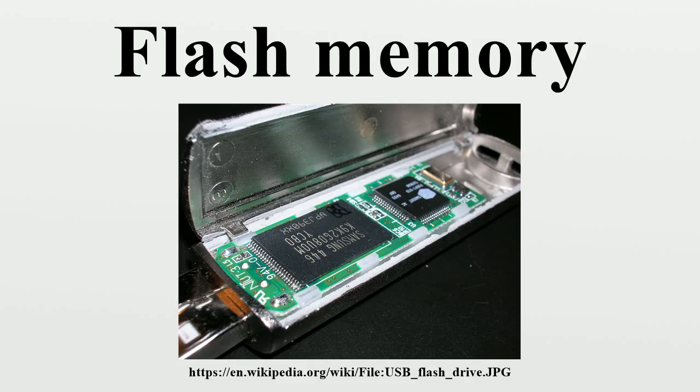Construction: growth of a group of NAND cells begins with an alternating stack of conducting polysilicon layers and insulating silicon dioxide layers. The next step is to form a cylindrical hole through these layers. In practice, a 128 GB NAND chip with 24 layers of memory cells requires about 2.9 billion such holes. Next, the hole's inner surface receives multiple coatings, first silicon dioxide, then silicon nitride, then a second layer of silicon dioxide. Finally, the hole is filled with conducting polysilicon.